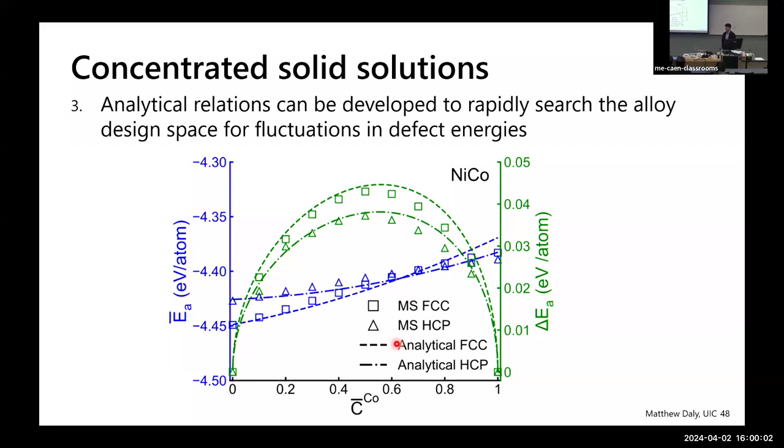Do you think this has tie-ins to some of the interesting properties of HEAs in general? Certainly, I hope so. That's what I'm staking a lot of my early research on. But I'll be happy just by studying these fundamental problems. What's known about HEAs and why they got very attractive, I would say, in the first point, is they have a very high solute hardening limit that has to do with the chemical environment. Now, we understand, modestly, what that solute environment might do to the stress to move a dislocation step by step. What we don't necessarily understand is when you have many dislocations interacting, how that will change the aggregation of defect mass deformation over at mesoscales. That's what we're trying to move towards. So we have maybe even a clumsy understanding of how that happens in pure metals, but certainly not in these complicated solute environments. So I guess the answer to the question is I'm not sure, but I think so, because most of my training tells me it should.